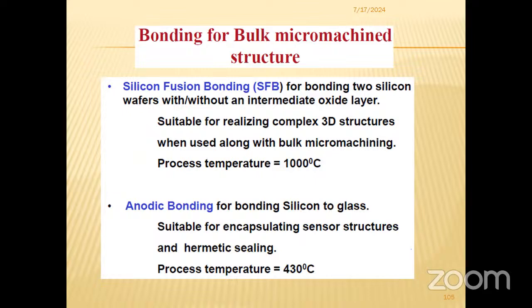It is not that easy a process, because the glass and the silicon should be bonded properly. For that, we should know what is fusion bonding and what is anodic bonding. For fusion bonding, the process temperature is 1000 degrees centigrade. For anodic bonding, the process temperature is 430 degrees centigrade. For fusion bonding, we actually bond complex 3D structures. But when we are bonding the silicon structure on top of the glass substrate, we go for anodic bonding. So silicon to glass bonding is anodic bonding.